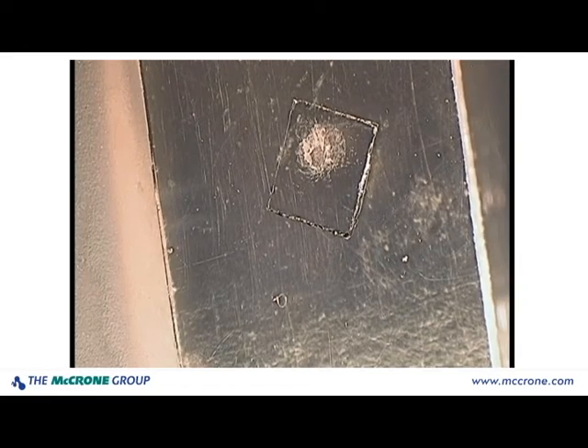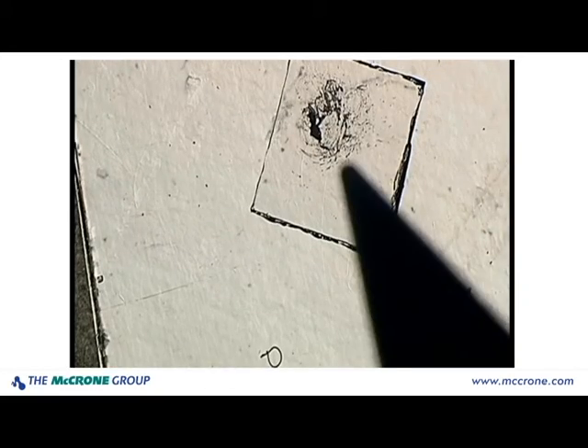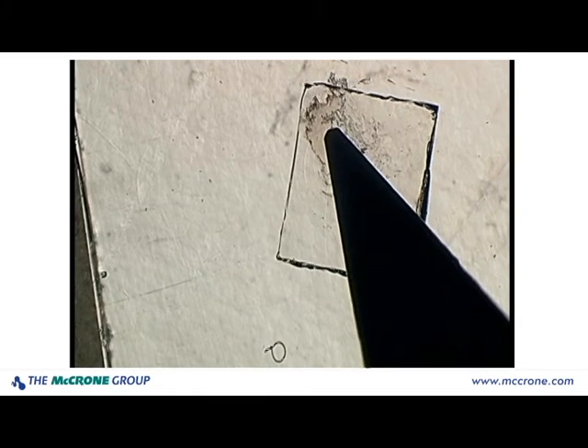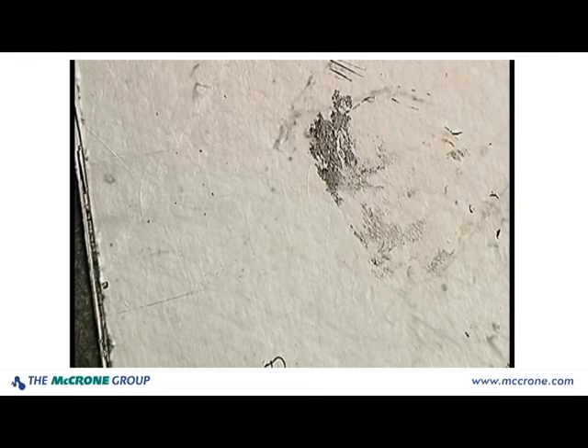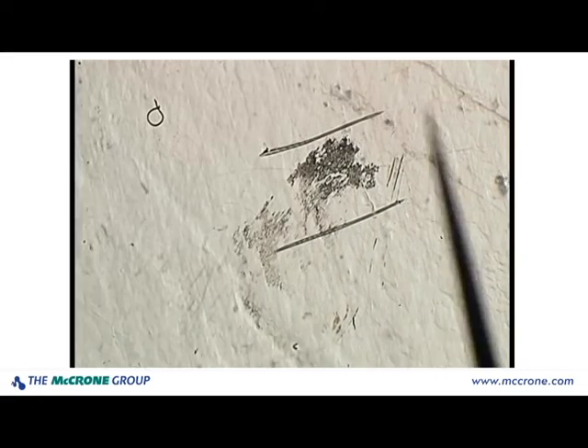You can then apply pressure again with your carbide scribe to the top of the cover glass and drag it away from your sample. This transfers that residue then to your KBr crystal, leaving a nice thin film. I always come in with my needle, the side of my needle, and scribe a box around my sample, which makes it easier to relocate my sample once it's in the instrument.